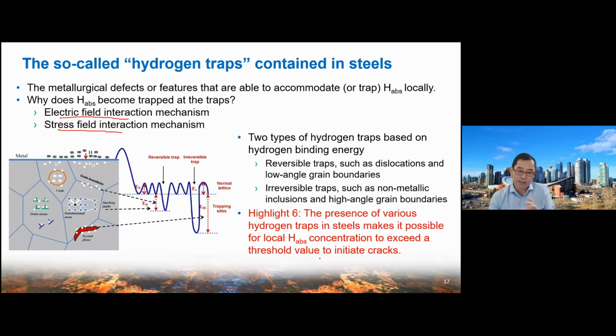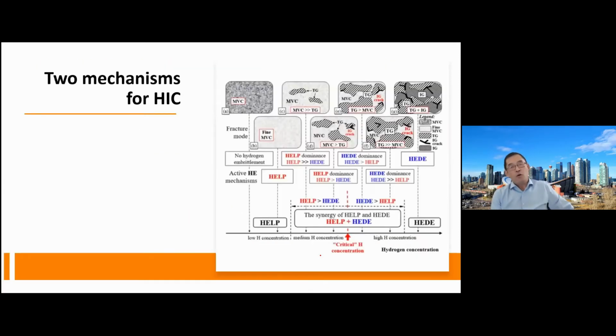So that's why, from this description, if we want to study hydrogen embrittlement or hydrogen-induced cracking, it's very critical to characterize the hydrogen traps in the steel, because hydrogen will pretty easily concentrate in these areas. Even if the average hydrogen concentration is very small, the local concentration is probably more than the threshold value to cause a cracking event. All right, so why can hydrogen reaching a certain concentration cause the cracking of the steel?